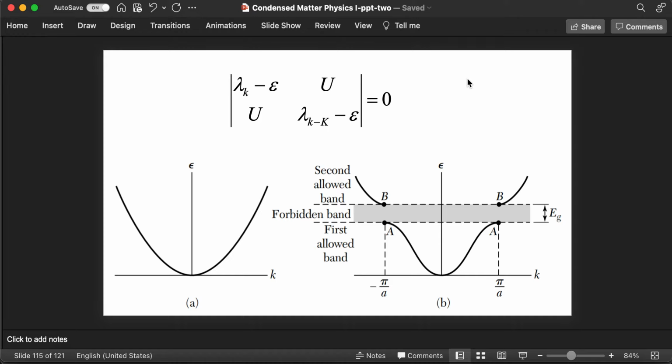On all the zone boundaries, there is Bragg reflection of the electronic wave function, and because of this Bragg reflection, traveling wave solutions become standing wave solutions at and near the zone boundary. Because of that, for the same value of the electronic wave vector, you get two solutions of the energy, one is A and one is B, and nothing in between. Therefore what was a continuous function for all other k values now has a band gap, and there are discrete solutions at the zone boundaries because of Bragg reflection. That is the origin of band gaps in a solid.